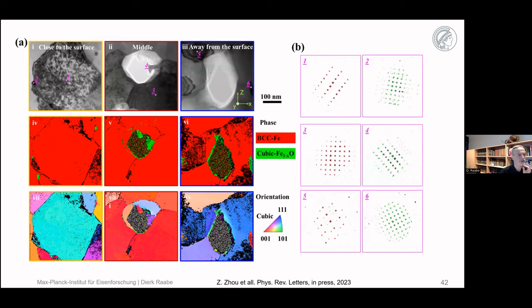Here's an example. It's a paper that was only recently accepted, now in press, where we studied the closed porosity. That means you have this micro-nano porosity everywhere in the material. And we discovered that when you look at it in high resolution transmission electron diffraction, you see that the inner rim around that pore is reoxidized. So this material was already completely reduced under the effect of hydrogen, and then it was reoxidized.